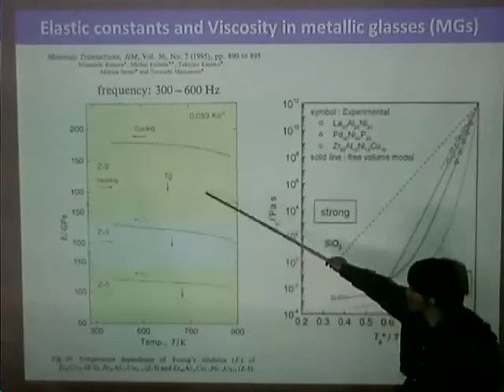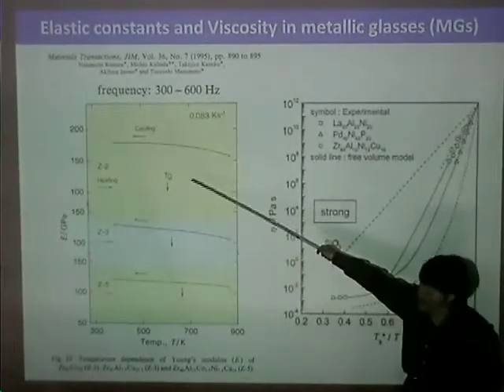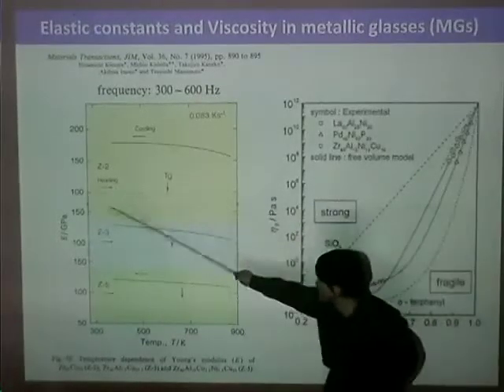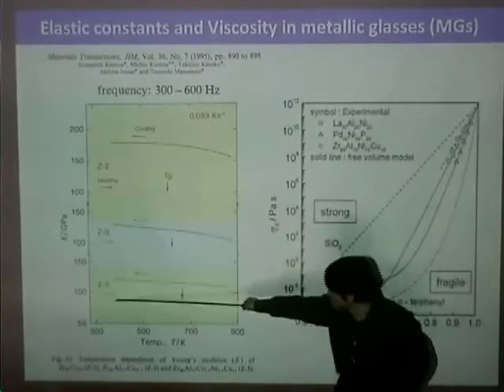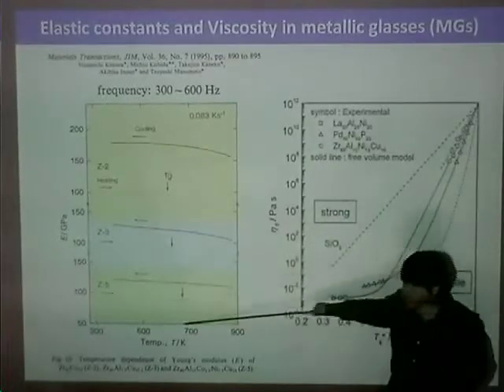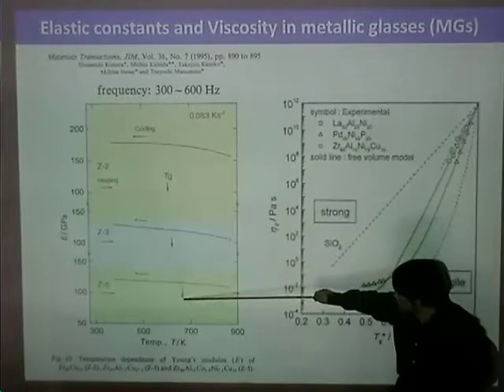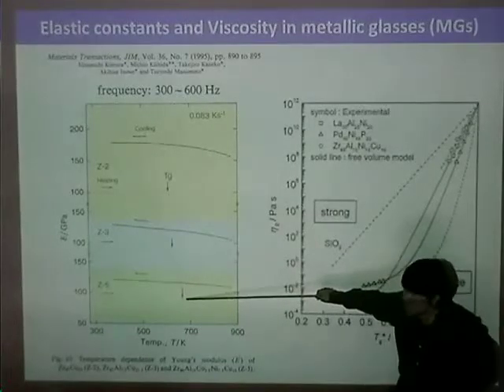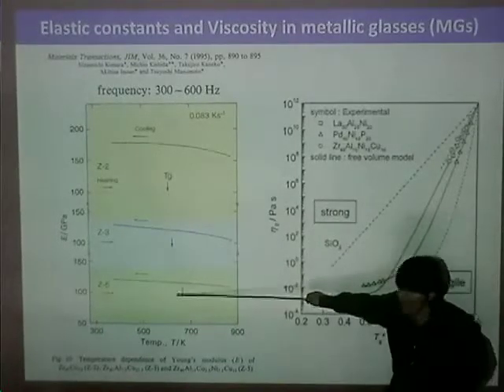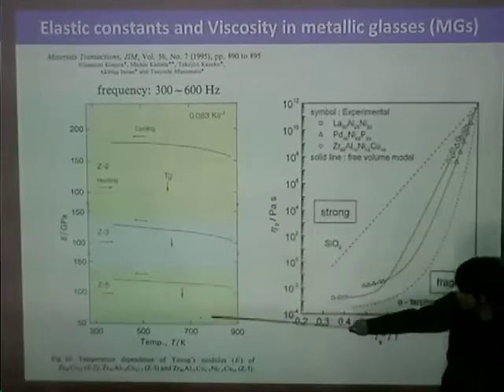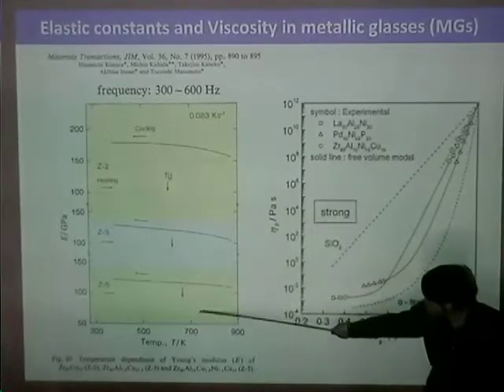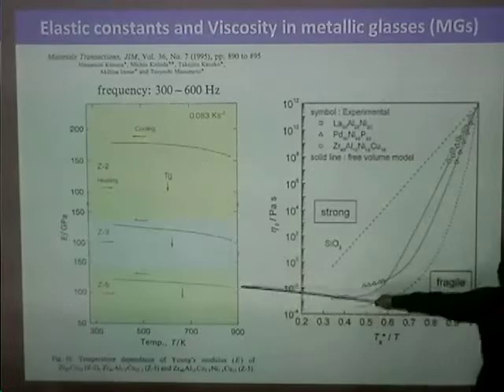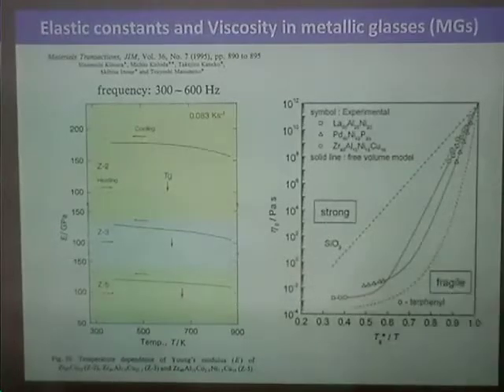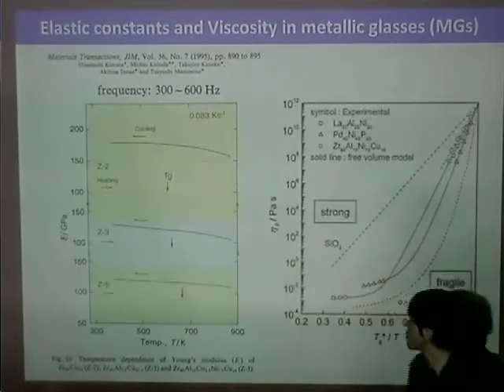This figure shows the typical temperature dependence of the elastic constant of the amorphous alloy. The elastic constant decreases with increase in temperature, and it continuously changes around the glass transition temperature. And at the crystallization, it rapidly increases like this. So this is the typical temperature dependence of the elastic modulus.